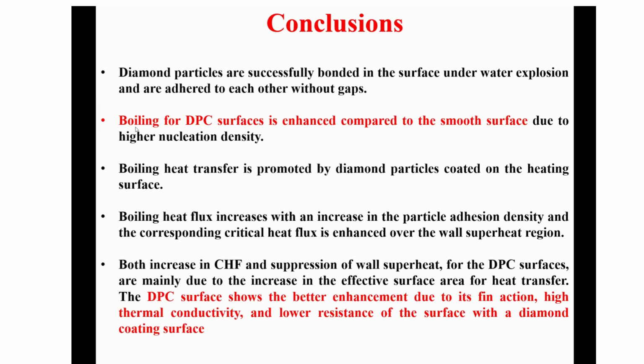Both the increase in the critical heat flux and the suppression of the wall superheat on the DPC surface are mainly due to the increasing effective surface area for heat transfer. The DPC surface shows better enhancement due to the fin action, high thermal conductivity, and low resistance of the surface with a diamond coating.